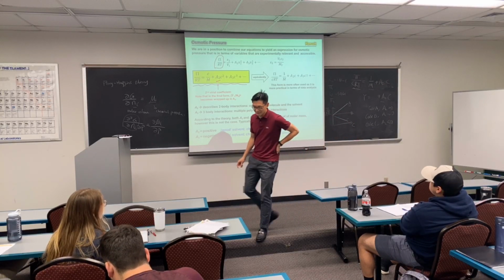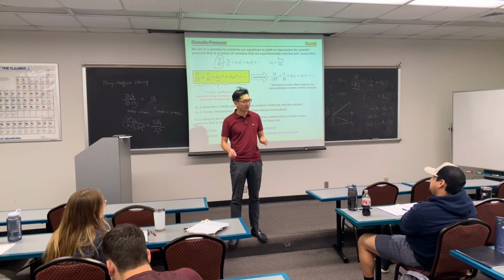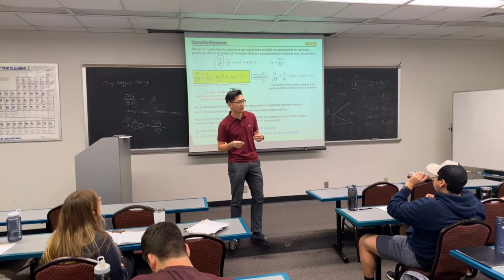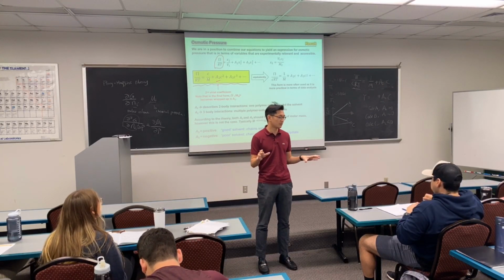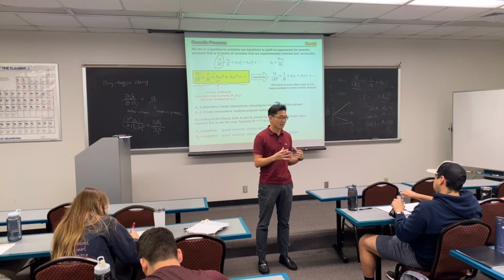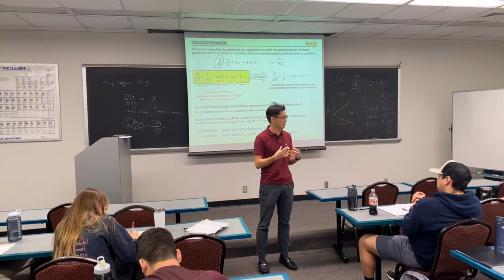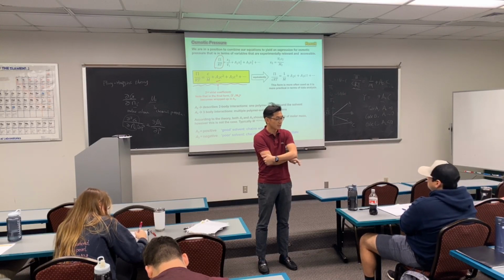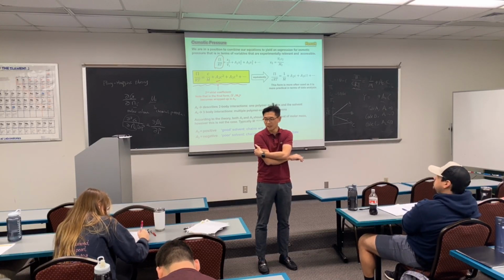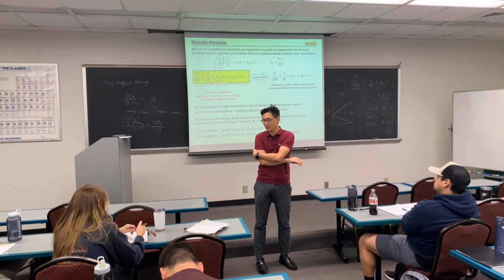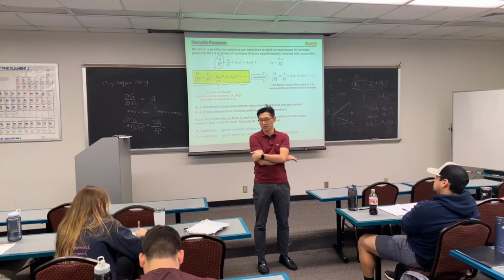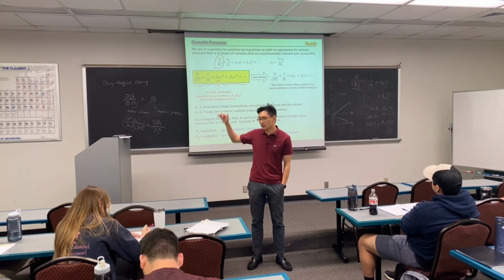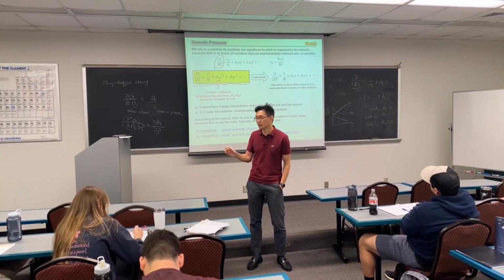Right. So in the theta solvent, the polymer doesn't contract because your interaction with yourself is sort of screened out by the effect of neighboring chains. So your chain itself behaves like a Gaussian chain. So in the theta solvent condition, your osmotic pressure will go up with concentration, but it will not curve up because this A2 term is 0. Okay?